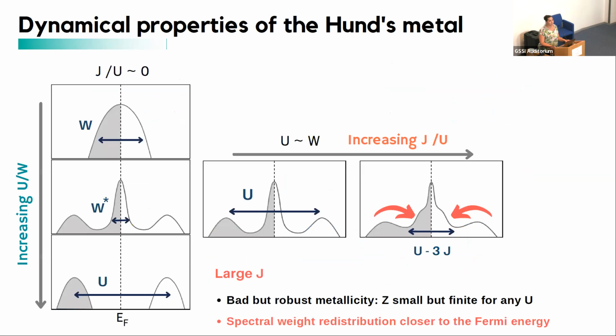The other point that I highlighted before is how the spectral weight is redistributed. There are a few studies on this, and I prepared this sketch because showing you real spectra could be confusing. But essentially, the message is that while before the redistribution was on an energy scale of order U, that is an energy scale of order of an electron volt usually, so it's pretty far away from the Fermi level, in the Hund's metal, the energy scale that controls the spectral weight redistribution is much smaller. So essentially, you have a coherent peak that, as I showed you, is extremely robust. So the system is metallic at very large U, and there is this kind of shoulder of spectral weight that is incoherent, but is living very, very close to the Fermi level.